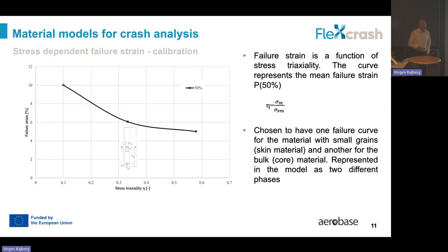Another thing with failure strain is that it is dependent on your stress state. So we usually define it with something called the stress triaxiality, and that is the stress condition. Typically in a uniaxial tensile test like this, where you have a hole in the center, you have a value of 0.33. If you have more shear-like behavior, you get close to almost 0. And in plane strain condition, you have approximately 0.58.